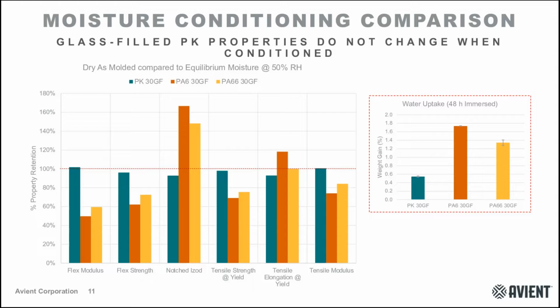In terms of your flex properties, your tensile properties, they primarily drop off, with the exception of tensile elongation, which increases a little bit. It's interesting to note the notched IZOD impact actually improves a lot for glass-filled nylons. And this is because water actually plasticizes nylons and makes them more impact resistant. So this can be a benefit for things like nylon 6 and 6/6. But ultimately, what we're trying to tell you here is that polyketone is going to have similar properties, dry as molded, as it will have in its final end use.